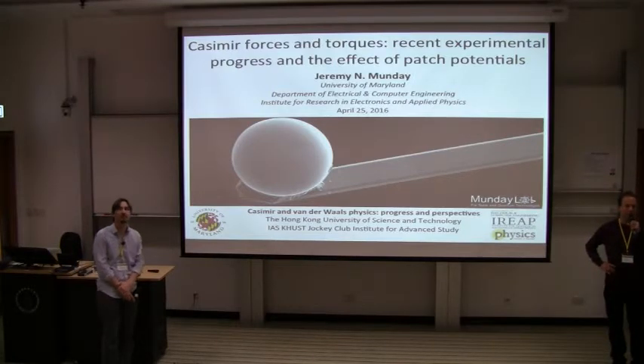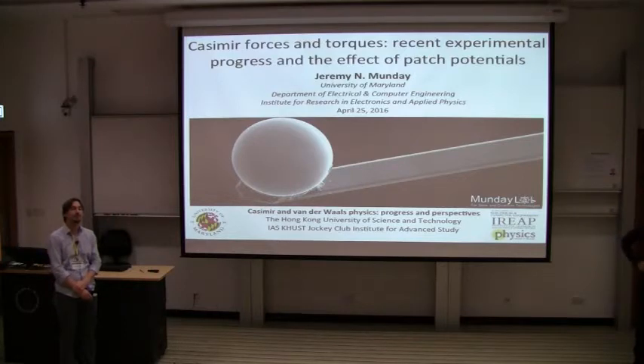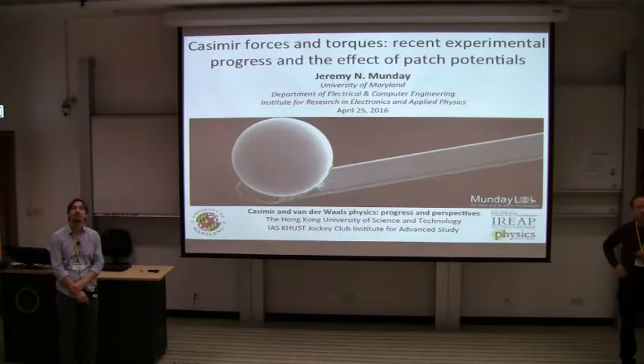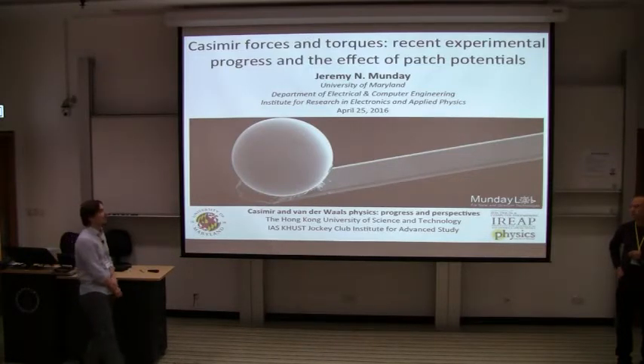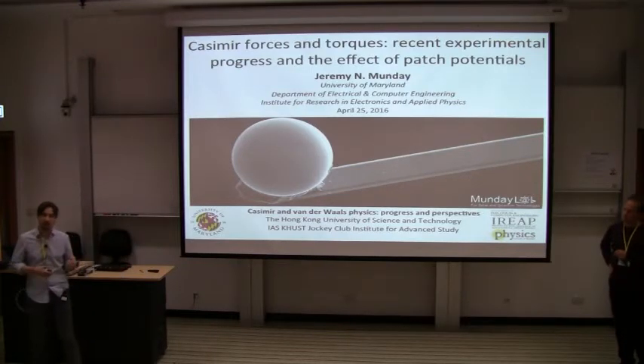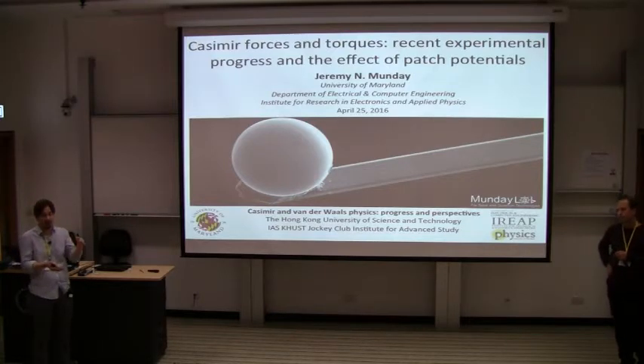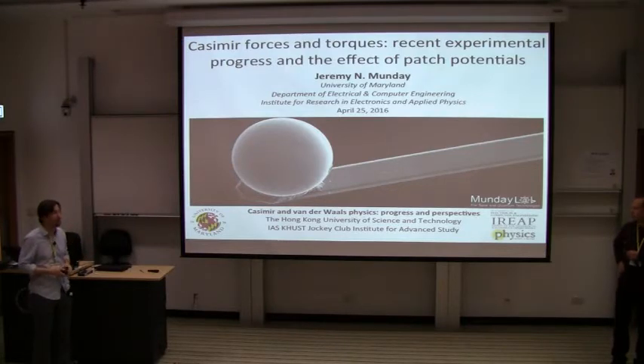Okay, Umar from the back. I was just going to ask for your comment on the patch potential measurements, which were done in air with different humidities, as you pointed out. Could you comment on how it will translate to the experiments, which are usually done at high vacuum? Yeah, so there are two things going on. Going from vacuum to air, usually you do get a little bit of a wetting layer, which actually suppresses it a little bit. So in air, you tend to get a little bit less contribution from patches. It also changes the distribution itself, whether they're small patches versus large patches. But we don't quite understand the results yet, so I wouldn't speculate too much on that. But it does depend on the humidity.